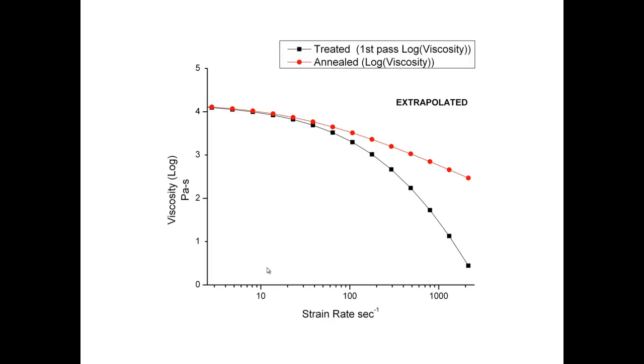And as it turned out, that melt didn't have a change. The treated melt, the first pass, is the same as far as the Newtonian viscosity. So the melt flow index is unchanged, and therefore you might think, well, we have done nothing to the melt. Well, on the contrary, if you compare the red and the black curve, you see that the melt shear thins much more. That means its pseudoplasticity has increased tremendously. If you compare at 2000 strain rate, the log of viscosity for the red and the black curve, this is huge.